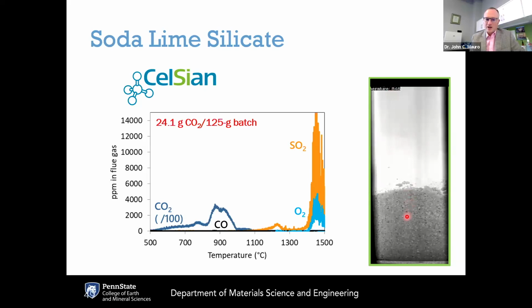You can see not much is happening, at least visually here, even as we get close to 900 degrees C. Here we're starting to see a few reactions, but it's kind of slow coming. On the left, you can see the gases measured by the gas chromatograph. The CO2 is actually divided by 100 here just to fit on the same scale as everything else. If you integrate the CO2 here, you get a total of 24.1 grams of CO2 released for this 125 gram batch.